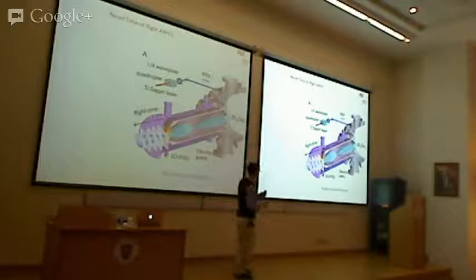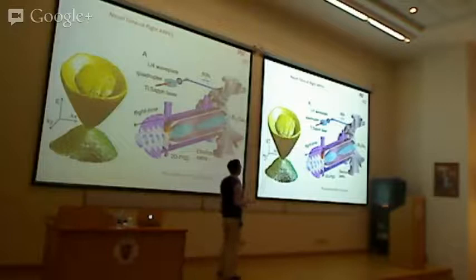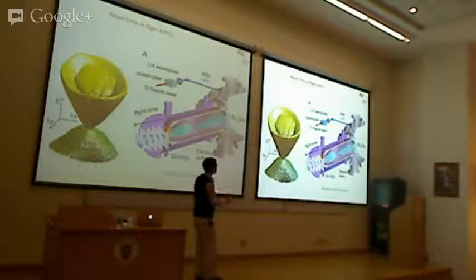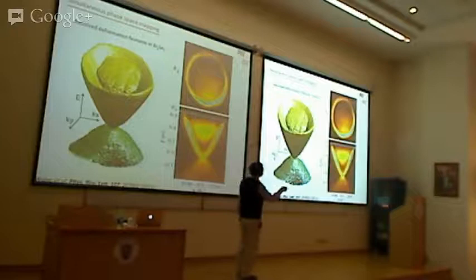The data we get is three-dimensional: energy, Kx, and Ky simultaneously. To the best of our knowledge, this is the first time anybody has done three-dimensional band mapping in any material. You can see the Dirac cone and bulk states. You can cut it vertically or horizontally — for example, at the Fermi level you can see the hexagonal warping I mentioned, the fact that the constant energy contour is no longer a circle at high energy. You can also see the surface state and bulk state in cross-section.